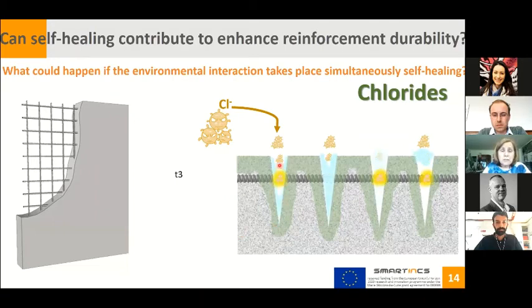However, we have a phenomenon of self-healing of the crack. The self-healing could only partially cover the crack, and then it's impossible to completely avoid the initiation of corrosion. It could be that there is a self-healing of the crack, however, that self-healing is not able to avoid the penetration of the aggressive agents, and finally the corrosion is initiated. Marta Roche was also showing some real response in this direction.